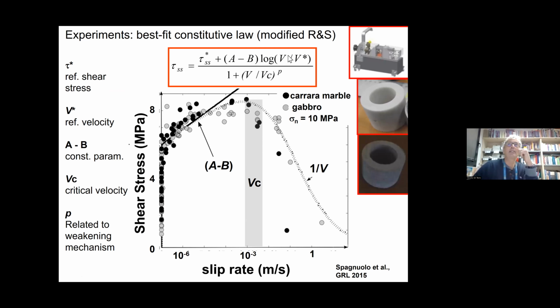And then we go back to what I don't like much, but is the best fit. So this is shear stress, this is slip rate, and you can fit this data set with this sort of constitutive law, where this is shear stress for a given velocity, okay? There is a threshold that you have to overcome. So depending on whether you're below or above this velocity of about 1 millimeter per second, this empirically based constitutive law works. However, this is based on experiments.